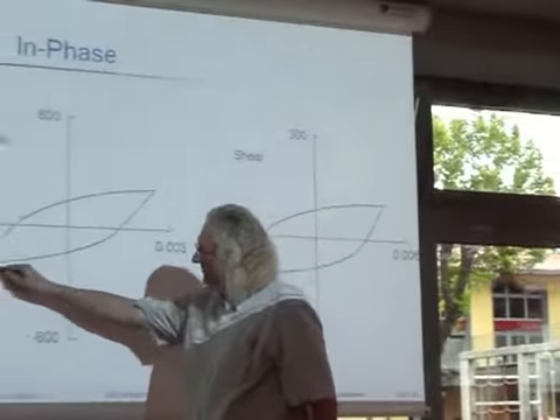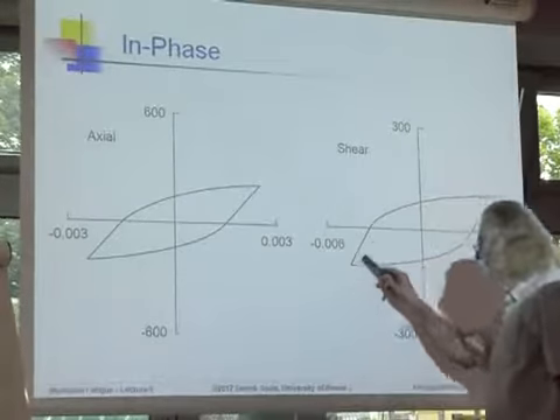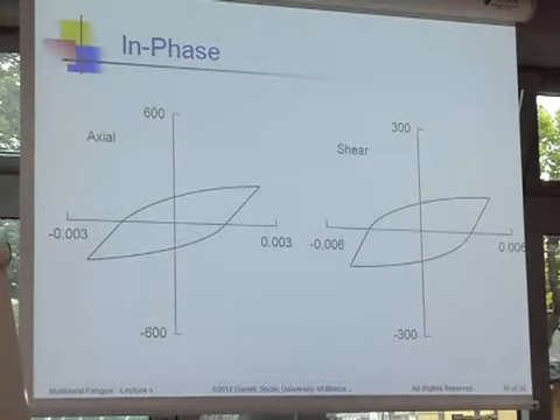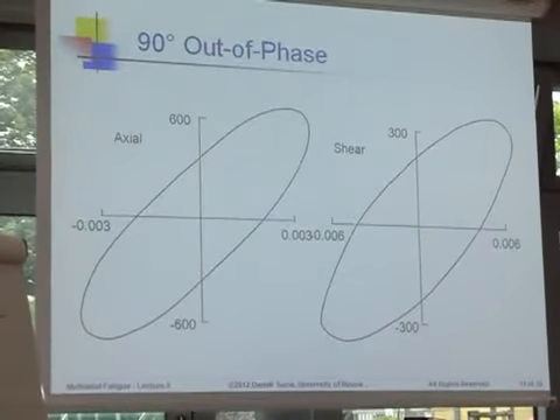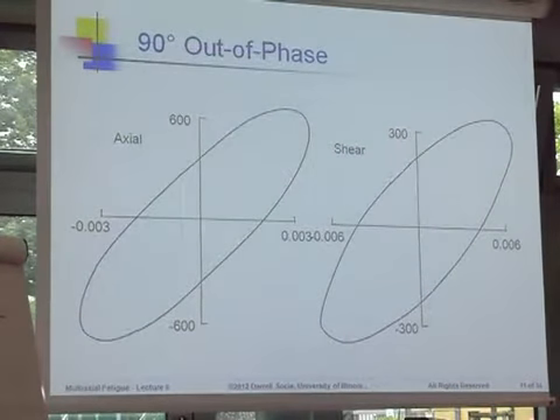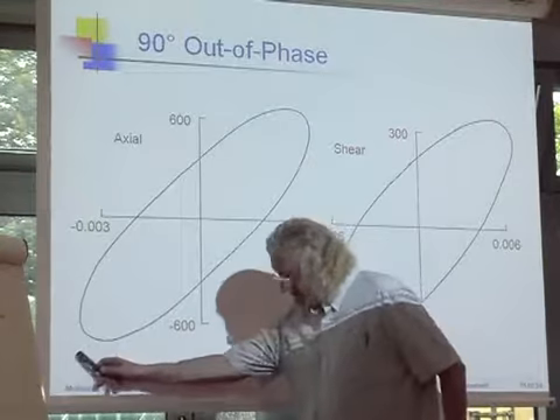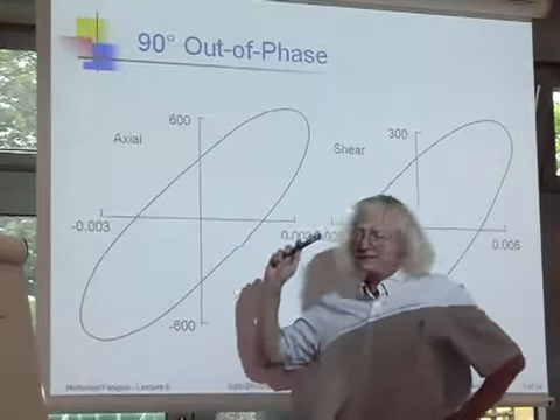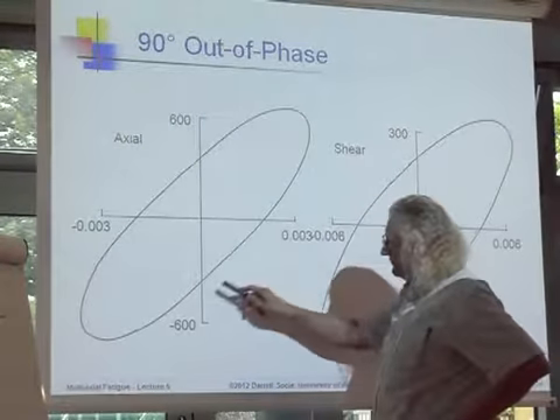And so as I am cycling this, I measure the stress-strain response both in tension and in torsion. And if I do that, here is the response in tension, fine, and here is the response in torsion. Let's do the tests now, and let's cycle this out of phase and record the same behavior. And this is what you get. Same strain ranges. And you will immediately notice the magnitude of the stresses. The first thing that you notice is that the hysteresis loops are not of the standard shape. Instead of being pointed at the ends, they have these rounded ends and they look like that.